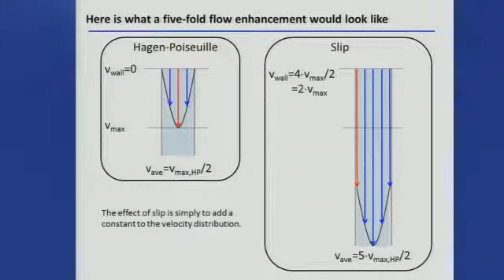The 5-fold flow enhancement, if you were to just visualize what that is, I did this calculation. This has a 5-fold average volume flow rate. And so 0 wall velocity here if it were Hagen-Poiseuille. So this gives you an idea of what the wall velocity would look like relative to the maximum velocity if you have a 5-fold flow enhancement. And so what's driving this improvement in chromatography then, or at least part of it, is that now you have this narrower distribution of velocities. So here you have a huge distribution. It's all and then nothing on the side, and there's a lot of area on the periphery of a circle. And here, this gets a huge head start on the periphery of the circle, and so you've got a much narrower distribution of velocities.